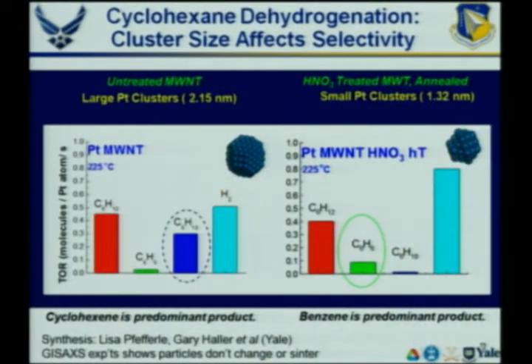So you can't probe before or after, you really have to probe during the experiment. So we've been able to do that, with some experiments at Argonne. In these experiments, it's cyclohexane dehydrogenation. So that's cyclohexane, a six-membered ring, losing hydrogen. It's losing two hydrogens at a time, and that's one of these endothermic processes. So it absorbs heat in doing it, but the products are still something that you can burn in your combustor. So it's a nice model system for an endothermic fuel.